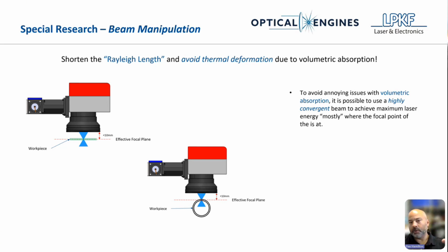And the rest of the part, for example, is in the diffuse part of the beam or the defocused part of the beam. This is especially helpful when doing microfluidic parts. Let's say there's channels on the top and you have to weld a film to a substrate, and there's channels on the bottom and you don't want to affect those channels on the bottom by thermal expansion, or you have to weld on the bottom as well. So kind of those two options. And we found that this works quite well to avoid any of the thermal expansion, volumetric absorption and expansion down through the part completely. The same can be held true for radial welding, as you can see with the bottom here.